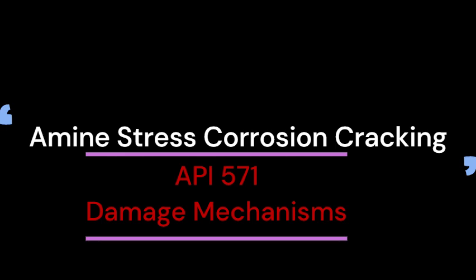It can be challenging, especially on existing welds and piping. It's often very difficult for the UT signal to reliably distinguish between an actual amine SCC crack and maybe some small harmless flaw that was already there from when the pipe was made, like lack of fusion or something. The signals can look quite similar, so caution is needed interpreting UT results for this. Okay, good to know.